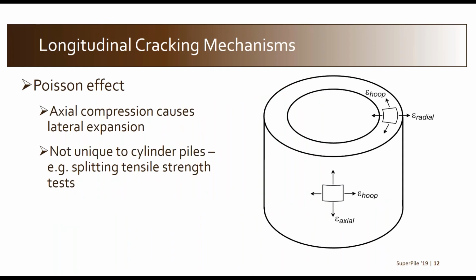Okay, so looking at the Poisson effect, this applies to all engineering materials, at least most of them that we deal with, which is that when you put an axial compressive force onto a material, it wants to expand in the other orthogonal directions. So here that would mean when we're putting an axial compressive force down the pile from the pile driving or from the pre-stressing force, it has a tendency to want to expand in the radial and hoop directions, as defined graphically here. If you think about what would cause a vertical crack to form, it's tension in the hoop direction. We have to have this thing pulling apart in order for a crack with that orientation to open up.